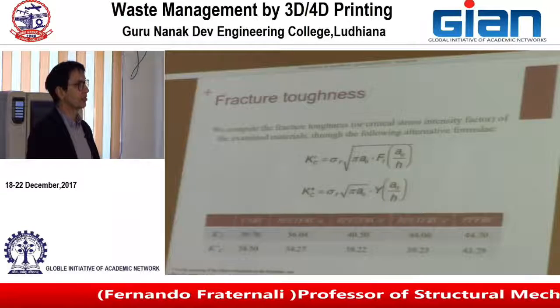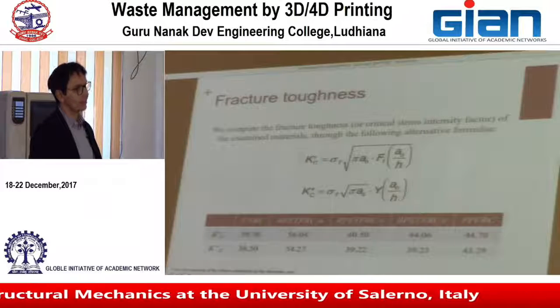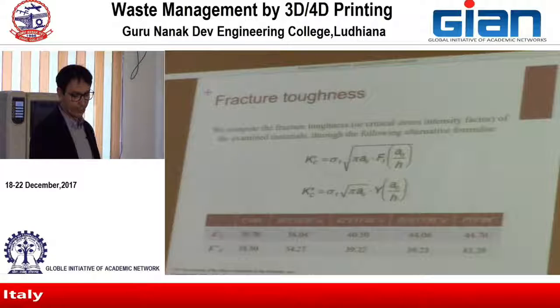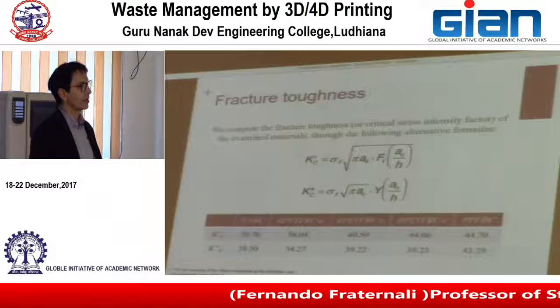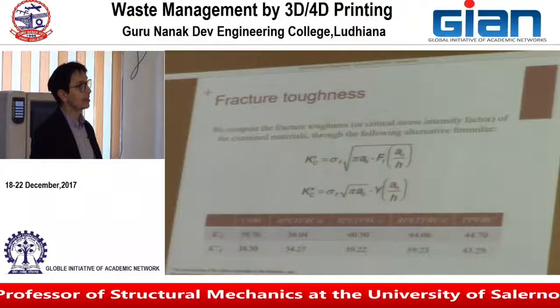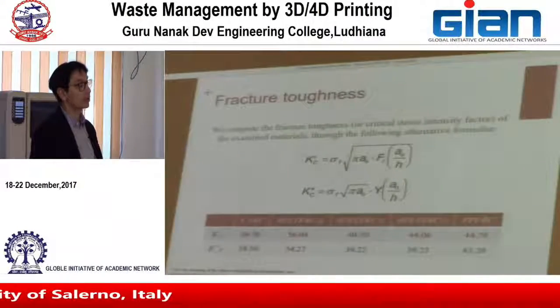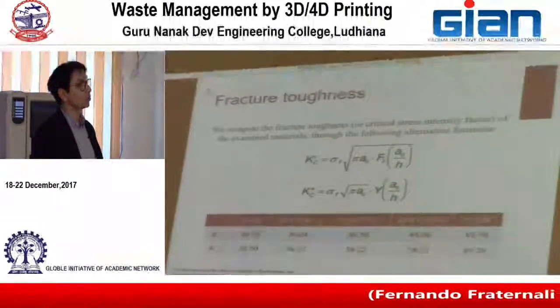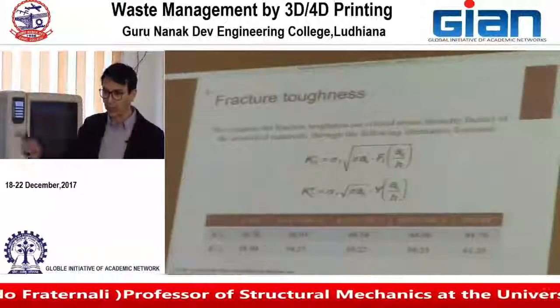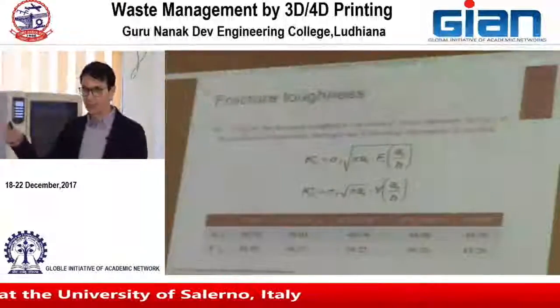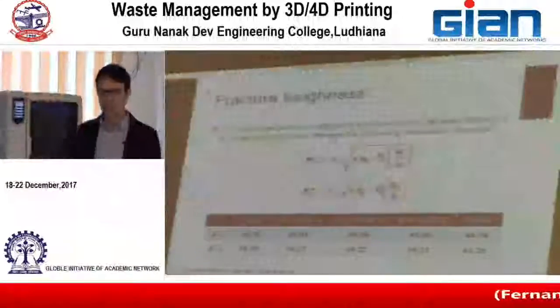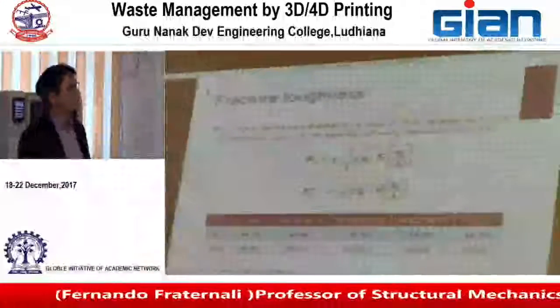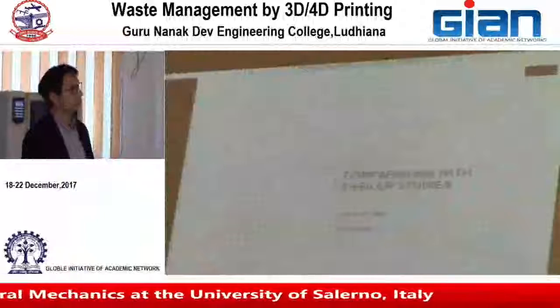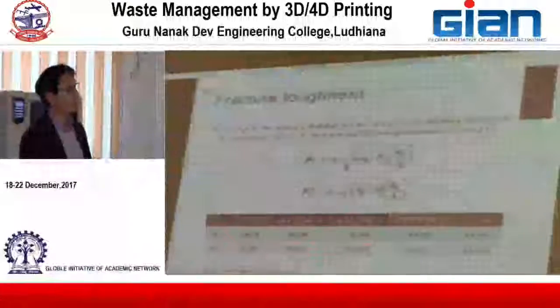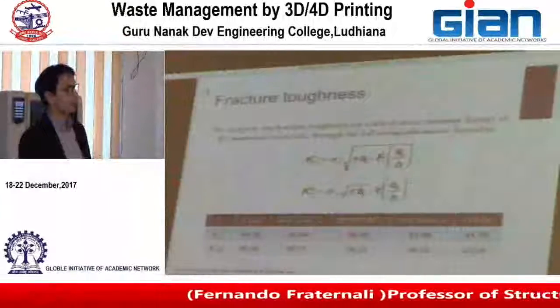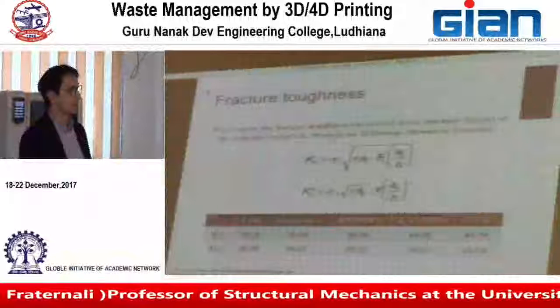We also measured the fracture toughness, which is somewhat related to the above quantities, but it's a different quantity according to the theory of fracture of materials, and these are the fracture toughness values obtained according to alternative formulas. The fracture toughness is proportional to the area underneath the force crack tip opening displacement curve, and is a measure of the energy dissipation capacity of the material. What we obtained was that also in this case those quantities were quite larger due to the addition of fibers as compared to the plain concrete. So the energy dissipation capacity was significantly larger.